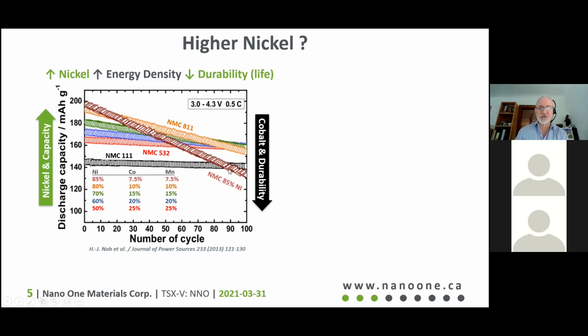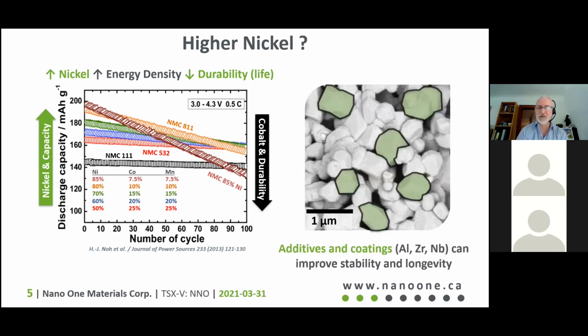This is the challenge: how do you get this as flat as the 111, but still get the higher capacity? As the cobalt goes down and the nickel goes up, you lose durability. One of the ways you can get around this is to add additives like dopants into the crystal, or you can add coatings based on alumina, zirconia, niobium to improve the stability and longevity so you get the best of both worlds. You get high capacity and good durability. And this is what everybody's going for.